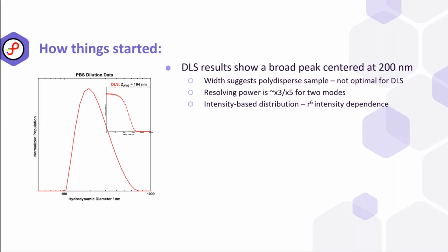Now, from my eye, which I've had, again, way too much experience with DLS, this is a very broad mode, and it's also asymmetric, which suggests to me that this is not a monomodal distribution. Now, the resolving power of DLS is somewhere within a factor of 3 or a factor of 5 between two modes to fully resolve them. And this is an intensity-based distribution, so there's an R to the 6th intensity dependence. That means that the largest material is going to be far, far, far overexpressed in the experiment. And I think that's what's happening here: we probably have some larger material in here, probably from the reconstitution or the dilution, that's kind of contaminating that result.